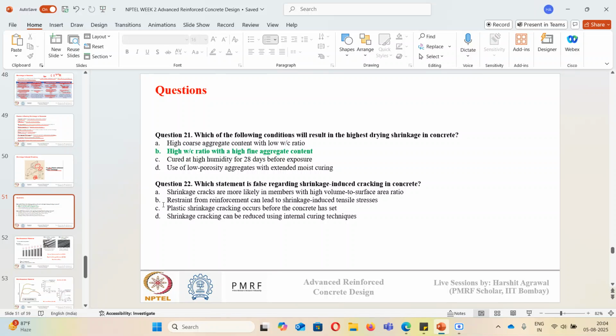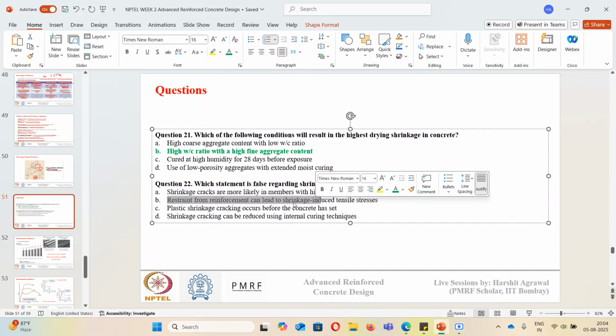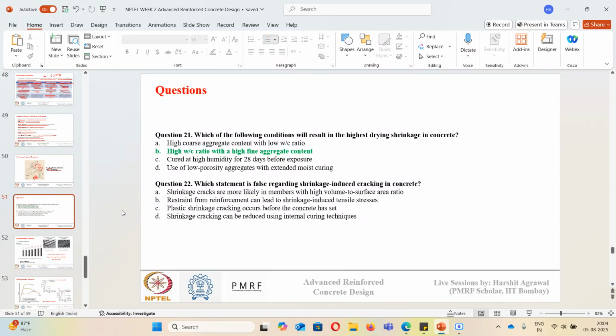B is also not right. B is also right, but it is not false. Restraint from reinforcement can lead to shrinkage induced cracking. This is also true. There is something known as the top bar effect. Okay, so what happens when there is reinforcement inside the concrete? When we pour a very flowable concrete, what will happen below the reinforcement? There will be a kind of air gap that will be created, and that can be a source where cracking can happen inside the concrete. So they can also lead to shrinkage induced tensile stresses inside concrete. This is a little advanced concept that I will try to cover later on. This is known as the top bar effect. Okay, if someone wants to refer.